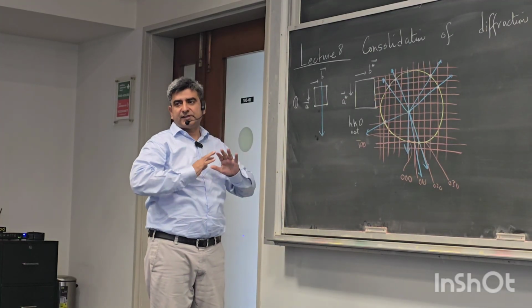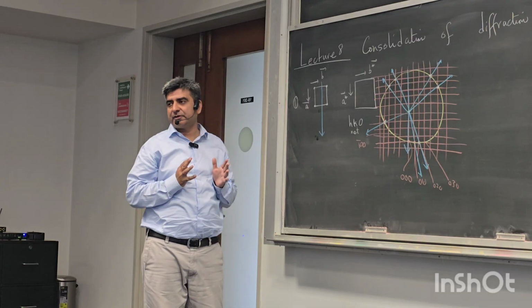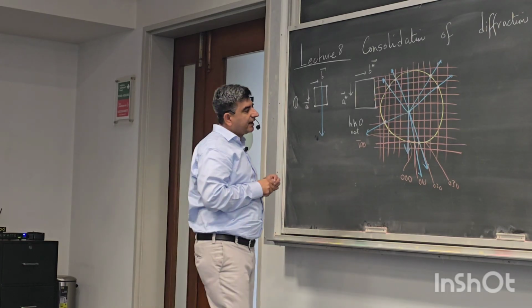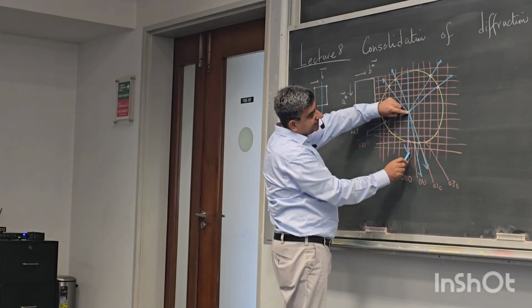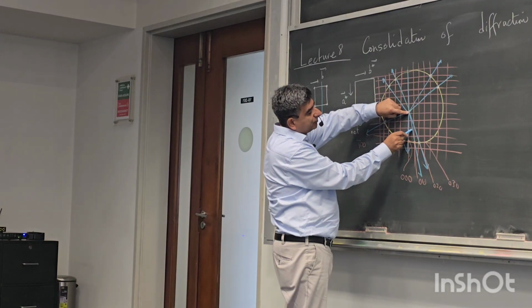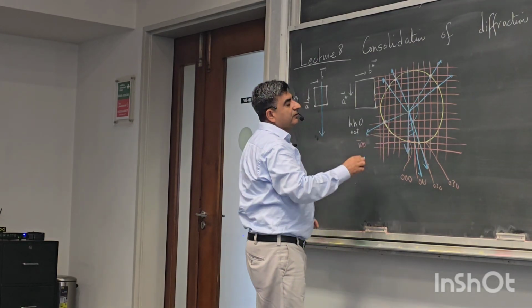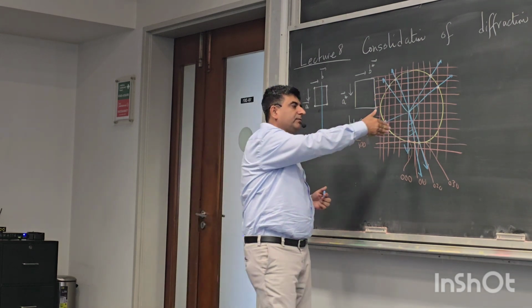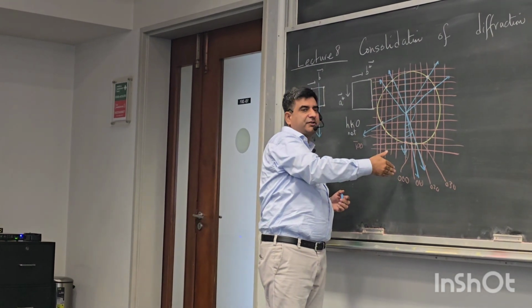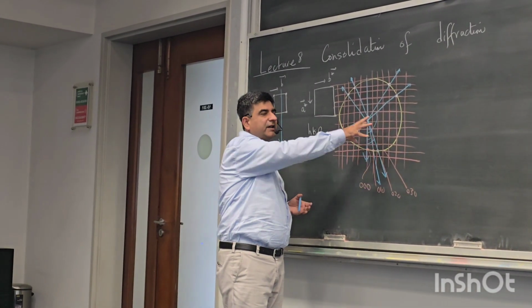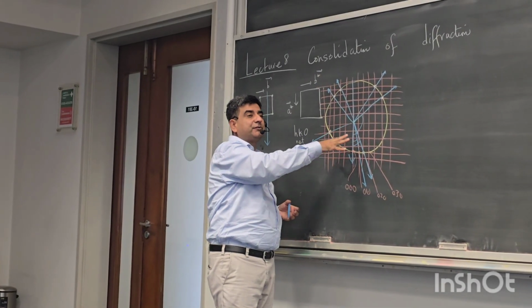All of this is consistent with the Bragg formulation as well. And these angles, so this is the incident X-ray direction. So angles of the scattered or reflected rays as measured from the incident X-ray direction, they are 2 theta. So reflections occur at these 2 theta values in this plane.